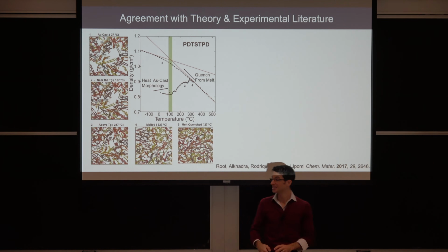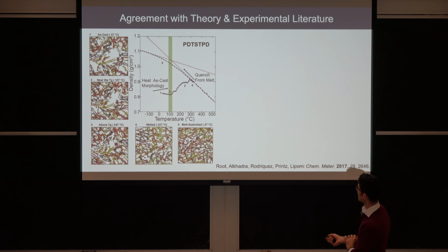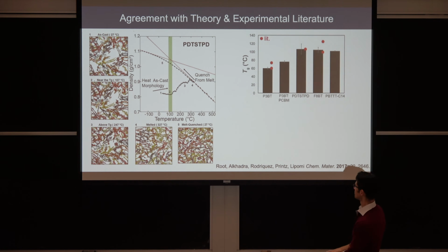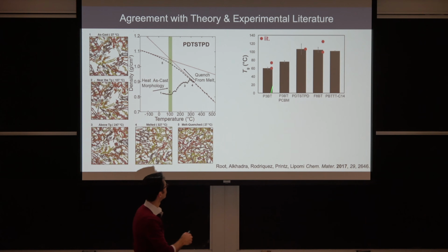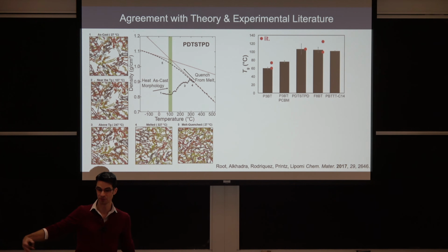So how well did we do? Turns out that our measurements can actually be verified, or supported, using atomistic molecular dynamics simulations. So, as you heat the material, the density increases around the glass transition temperature, and if you quench the material from the melt, so you cool it quickly from the melt, you get this intersection of these tangent lines, which also correspond to the glass transition temperature. So these are the results in the black bars here from the UV-vis data from our method, and then these dots here are the values from the literature. So we do pretty well.